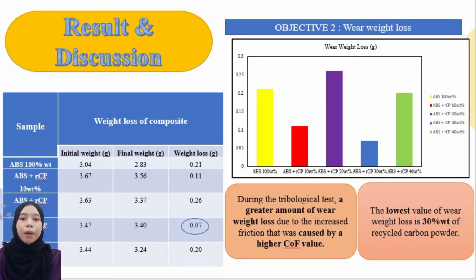Next, we go to the result of wear weight loss, which is the second objective of this project. The graph shows the average wear weight loss due to the wear on the ABS polymer composite. According to Surya and Parasanti 2022, the wear effect was determined through morphological observation of the surface and debris that had been eroded away. Sliding distance and load are the two most influential factors that control wear. During the tribological test, a greater amount of wear weight loss occurs due to the increased friction caused by a higher coefficient of friction value. The lowest value of wear weight loss is at 30% recycled carbon powder. This weight loss is included in the second objective.